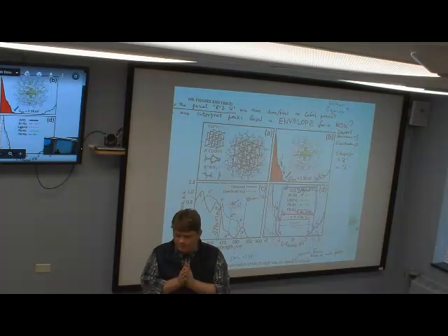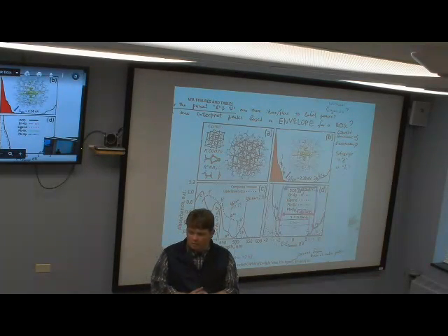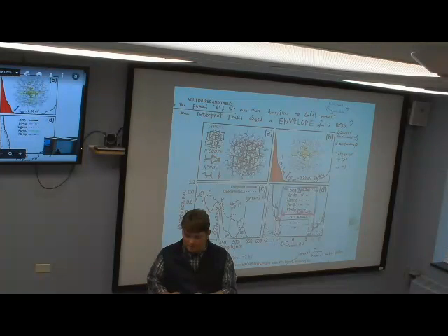and also based on the community effort in the quantum dot community, where most of the boxes were not three-dimensional boxes but spherical boxes, where each wave function is a product of atomic wave functions times an envelope. And the envelope wave function in a spherical container follows separation of variables for angular momentum and radial part, and therefore it shows the same progression of eigenstates with different values of angular momentum, like S, P, D.